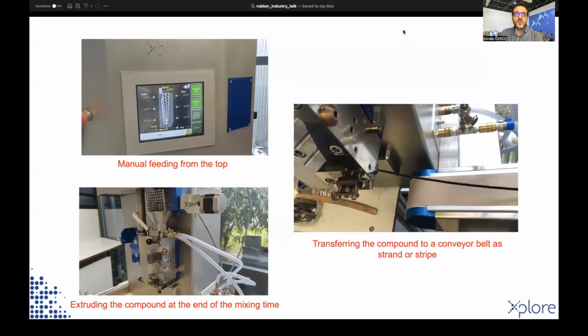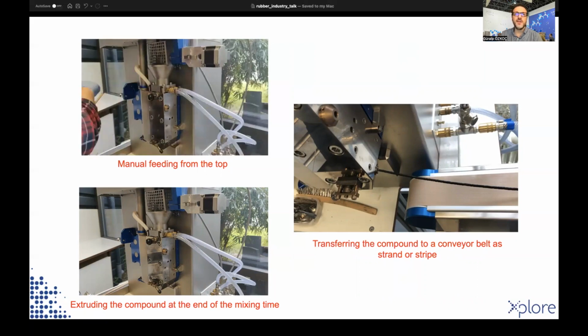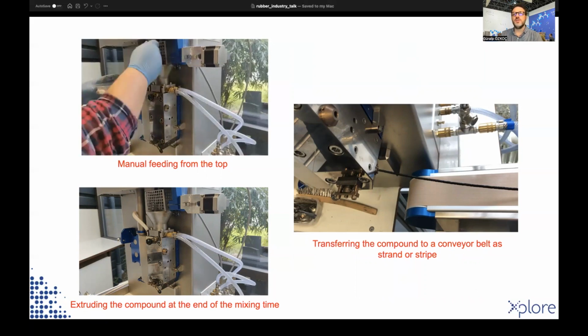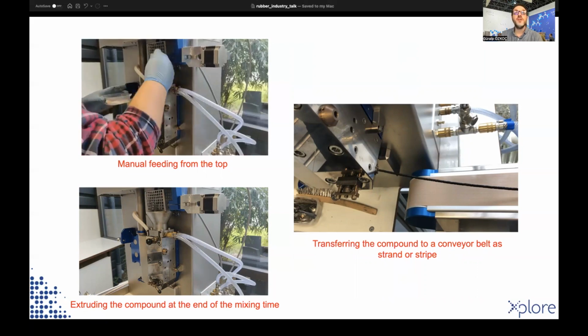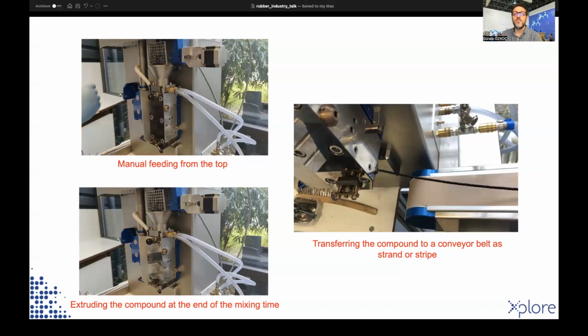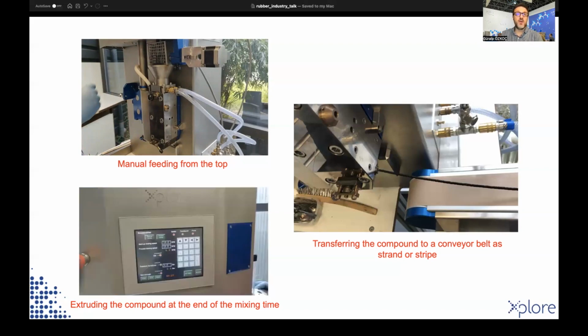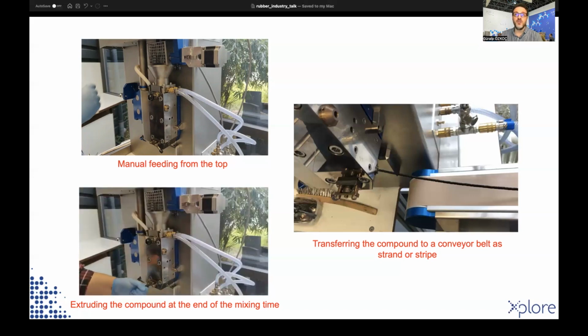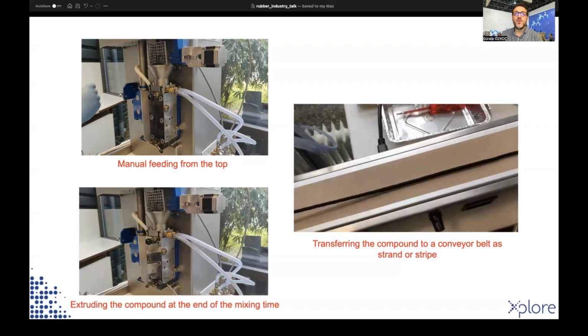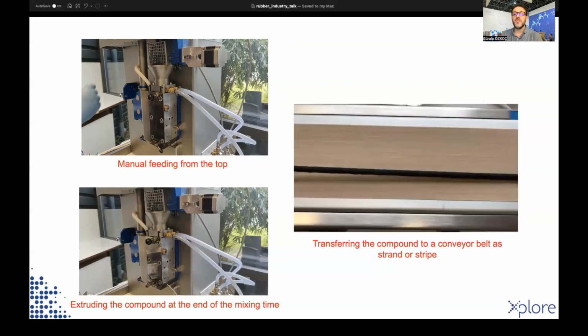In these videos, you can see the important steps of compounding process using the microcompounder. In the first video, on the left top, you see that the feeding of the rubber chunks and the additives such as fillers, oil, or cross-linking system is relatively easy. Please note that, as in conventional processing, we first masticate the rubber with oil and the fillers. Then, in the last part of the compounding, we normally add the cross-linking system. At the end of the compounding process, you can extrude the content by turning on the valve of the barrel. You can either extrude in a container or you can use our conveyor belt to take the extrudate easily.